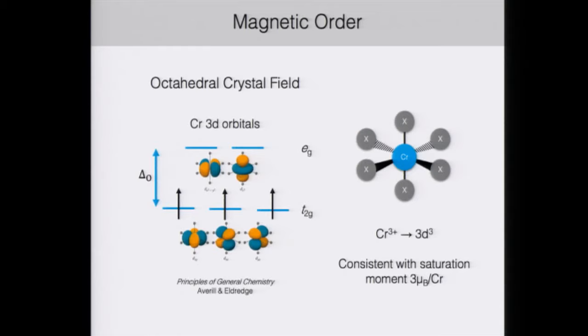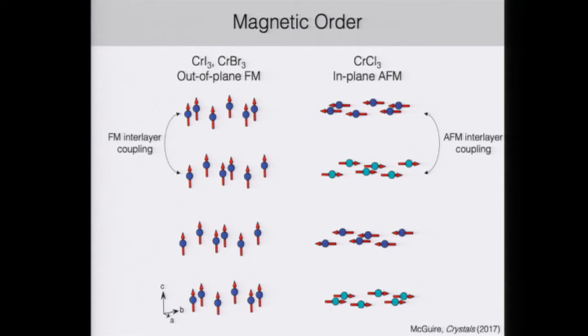The magnetic order can be understood by thinking about localized moments on the chromium ions. Chromium 3+ has 3 free d electrons, and we can think of it as being in a roughly octahedral coordination with the halide ions. In the octahedral crystal field picture, this gives us the t2g and eg splitting of the d orbitals on chromium. Since we have 3 unpaired electrons, we expect them to fill the t2g half-filled shell. This picture is consistent with observed saturation moments of about 3 Bohr magnetons per chromium site in the chromium trihalides. The ordering itself will actually depend on which halide ion is present.